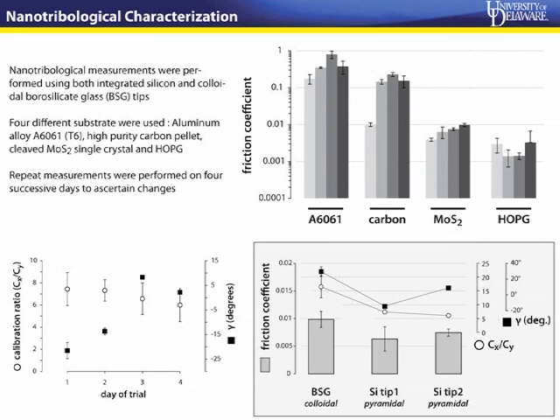This is really interesting because you'll notice that the calibration constants, although they're fairly close to each other, do vary between different days, and this affects the uncertainty that you cause by just removing a cantilever from the AFM and remounting and realigning the laser. The gammas also vary quite a bit, so that gives you a quantitative measure of the misalignments that you have.